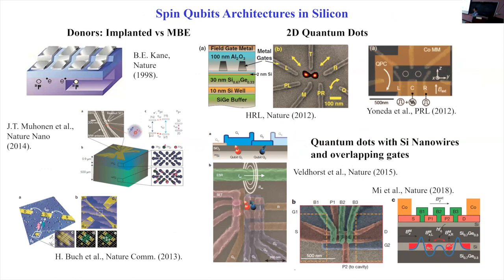Now in silicon, there are multiple ways people have now generated quantum dots, from the traditional 2D quantum dots with top gates and everything, to donors. And donors, you can implant them, just shoot donors, phosphorus, into silicon and then anneal it, to try to anneal away all the damage the implantation does to your silicon lattice, and then do experiments there, or you simply do MBE growth, which is extremely difficult, but it's still being pursued.